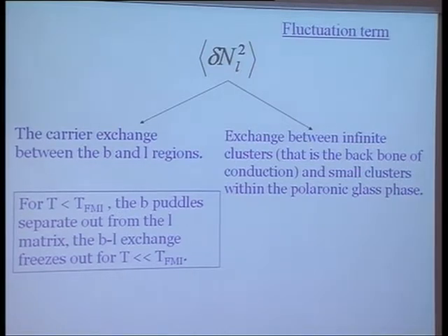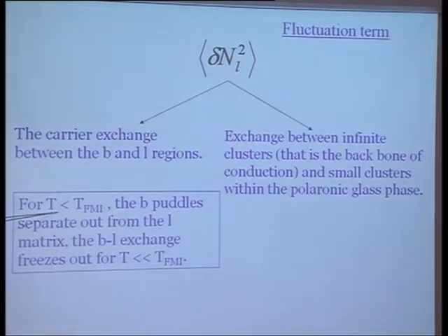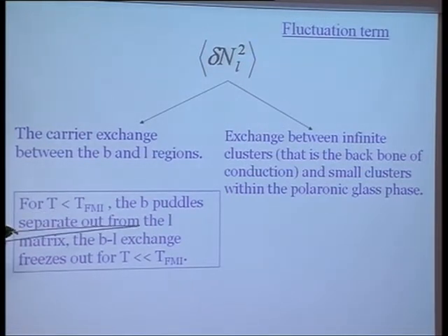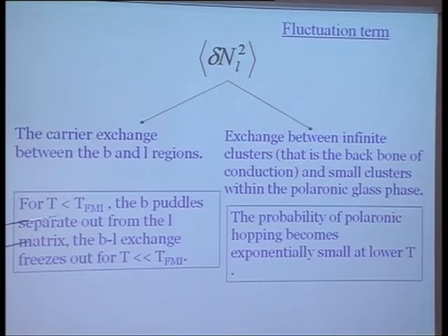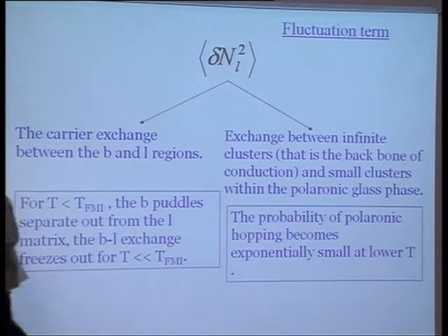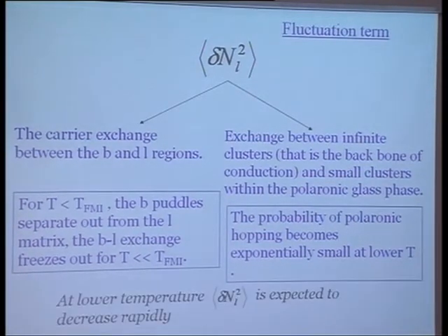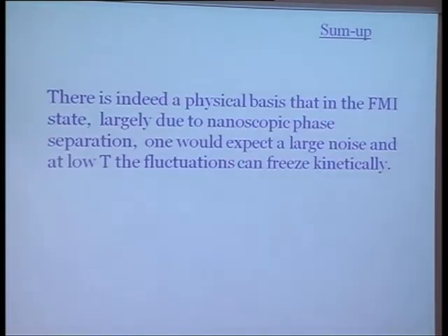Now, what we find is that when you are below the ferromagnetic insulating transition, as this B puddle and the L matrix are kind of separated out, the band type of electron and the localized electron exchange start freezing out as you go below the ferromagnetic insulating transition temperature. And also in this case, the probability of polaronic hopping becomes exponentially small at lower temperature. So both of them will reduce delta NL very drastically as you go to lower temperature, and this is what you are seeing as the freezing. So this is indeed what I say, that there is some kind of a physical basis that in the ferromagnetic state, largely due to its nanoscopic phase separation, there is indeed a large noise, and the fluctuation starts critically freezing out at lower temperature.